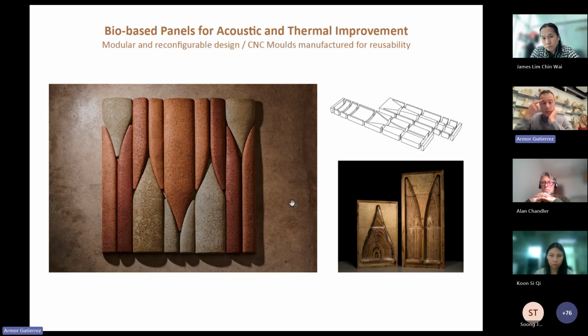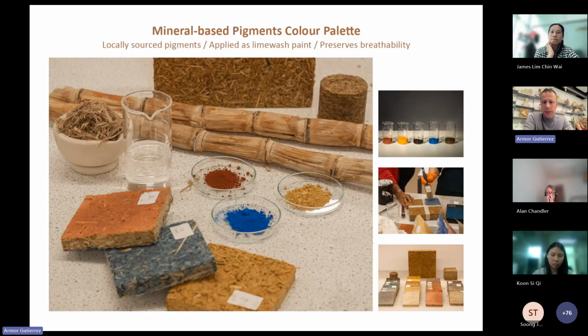Just by disassembling and reassembling the molds and then bracing them on the perimeter, you could achieve different sizes, which creates kind of dynamic geometry. The geometry is curved, as you can see, which means that when you unfold that geometry, you get much more surface than if these were flat panels, which is obviously beneficial for improving acoustic performance and for improving the reverberation time on internal spaces. And we did the mold that you see on the right here at the university with CNC facilities, and then we casted a set of panels as a test internally before the cast that you see on the left.